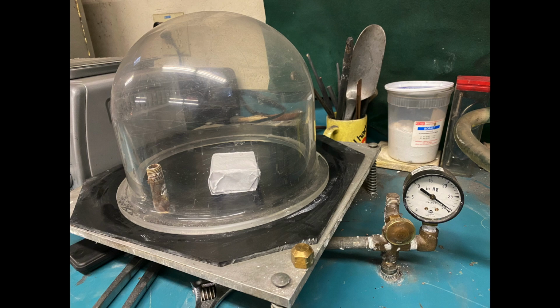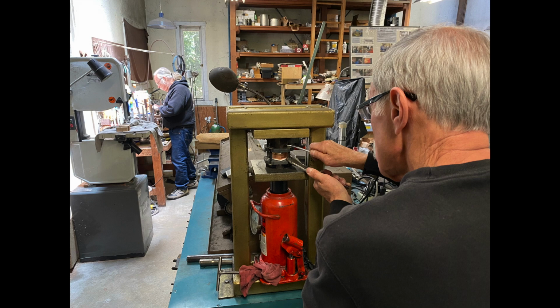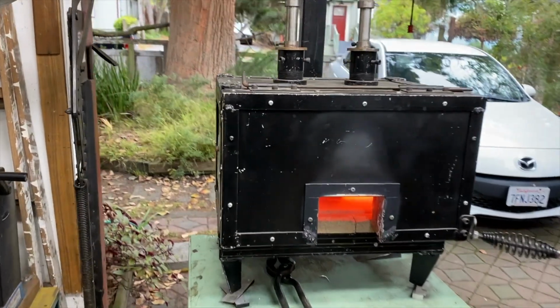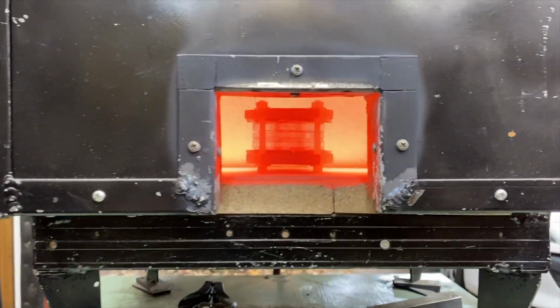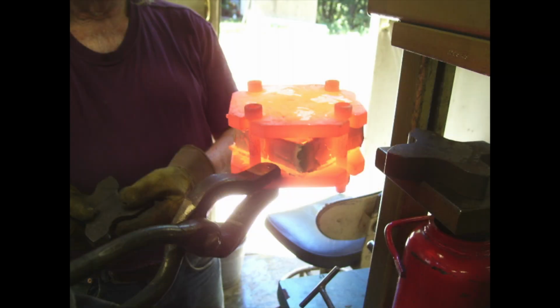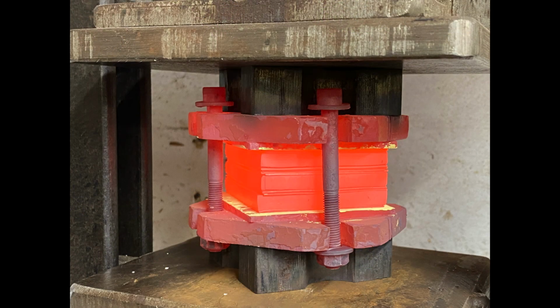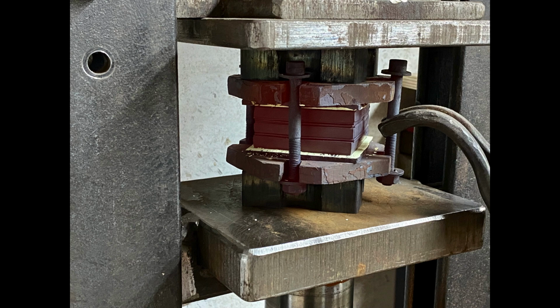If we need to, we can store them indefinitely in a vacuum. We press the plates under 20 tons of pressure in a hydraulic press. Then we heat them to fusing temperature in a gas forge. When still hot, we return to the press and squeeze the billet to consolidate the bonds and also to remove the bolts.